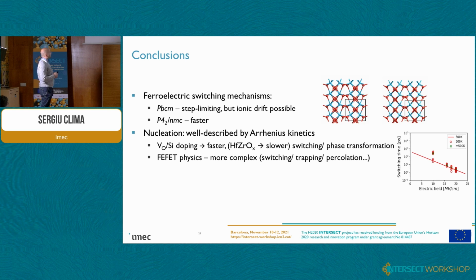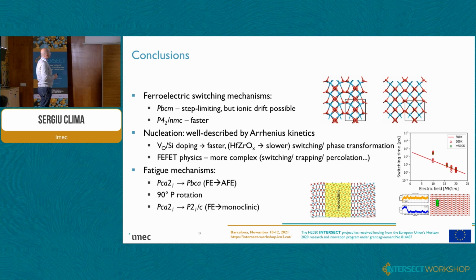We can have phase transformations, and those polarization rotations or phase transformations or 90-degree rotations of the polarization can account for fatigue mechanisms, and especially the transformation to the monoclinic phase will be one of the main failure mechanisms for this ferroelectric material.